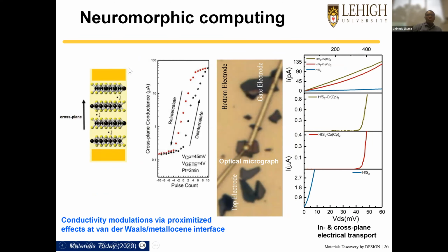Now, what we saw in this material is that you can both intercalate and deintercalate. I talked about this before. You can insert and remove those molecules. And this is a cross-plane conductance showing this hysteresis-like behavior where you can both introduce the molecule and also remove the molecule. So conductivity modulation via proximity effects proximitized at their interfaces. This is the optical micrograph.